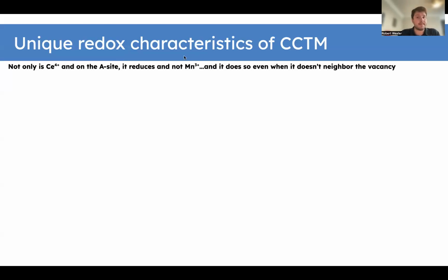But it doesn't. But manganese 3 doesn't reduce, cerium does. And it does so actually even when it doesn't neighbor a vacancy. So we can do calculations that show even when we form a vacancy that doesn't have a cerium in its neighborhood, a ceria nearby actually reduces, and not the material, or not the cations that are closest.